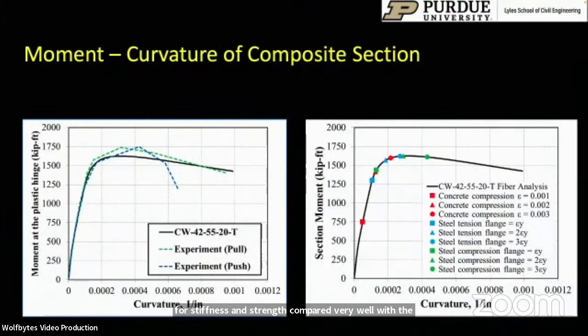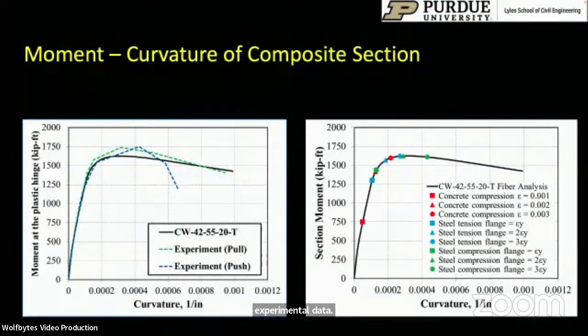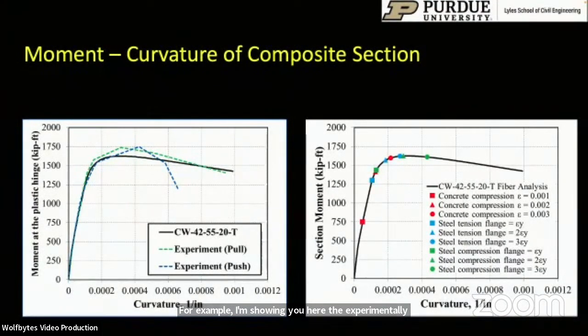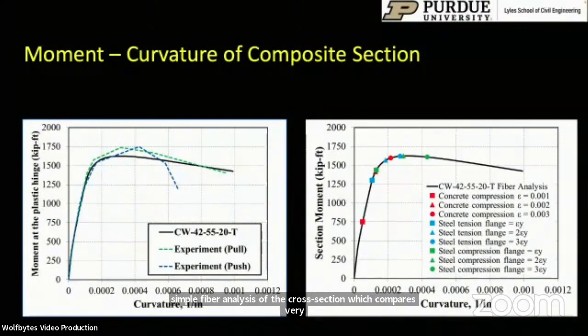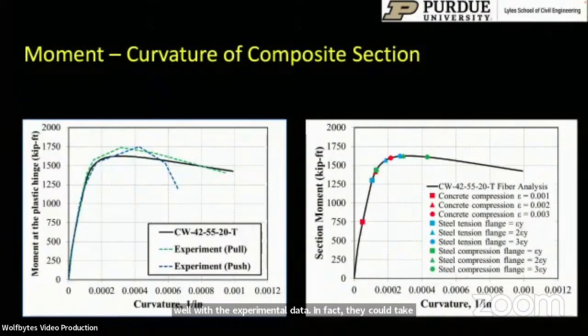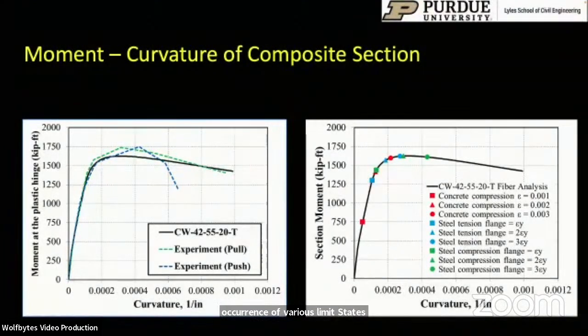For example, I'm showing you here the experimentally measured moment curvature response, which is shown with these dotted lines, and the solid black line is a simple fiber analysis of the cross-section, which compares very well with the experimental data. In fact, we could take that section fiber analysis and identify the occurrence of various limit states. For example, when does the steel reach a value of strain equal to 0.003? When does the steel reach a value of strain in compression equal to 2 epsilon y? We were able to identify the occurrence of various events.